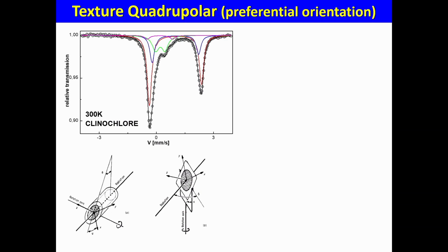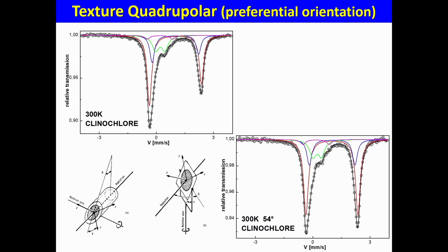So we know that in such clays, you have series of dioctahedral, trioctahedral layers. So we are rotating the sample. You see now an evolution of the doublet. And now you can fit with doublets with the same intensities of line. The reason here was the texture, the preferential orientation.